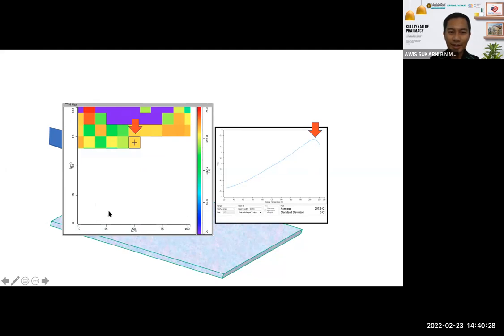So here, I think they have roughly 121 points. After we're done at this point, they're going to lift up, lower down the probe, and test the transition temperature of the next point. They're going to repeat all these points, and then after that, it's going to make a map of the temperature of each of the surface area. So at this point, you can get the idea of what material you have on the surface of the sample. Because normally on the sample you have an API and you have the excipient, for example, so they can map where this excipient is and where this API is on the surface of your sample.